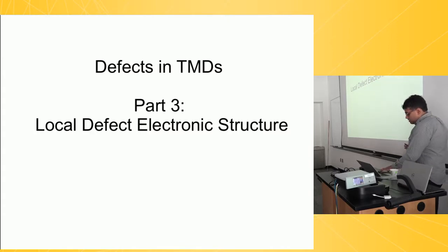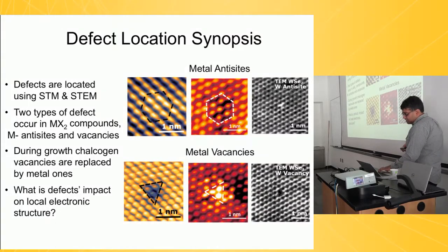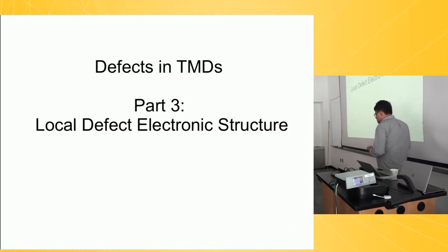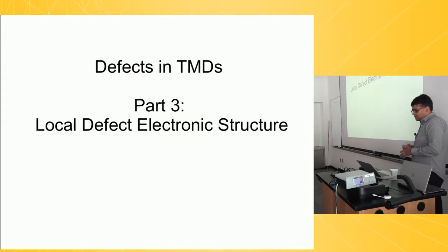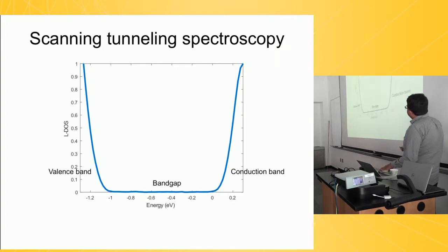Fine. So we've seen what these defects are. One of the things you can do in STM is go down with atomic resolution, measure the spectrum on these defects, and ask what these defects look like spectroscopically. That's the next thing we did. A little primer on STM spectroscopy: what you do with an STM is essentially an IV measurement. You sit at a particular point in space, change the voltage, and measure current. If you do this for a semiconductor, in this case molybdenum telluride, which I'm going to tell you about, what you measure is a spectrum that looks like this.